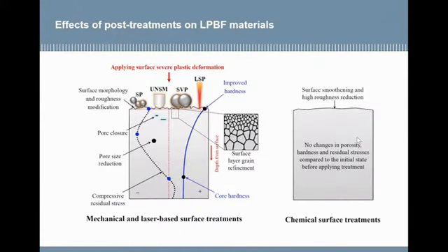The mechanical surface treatments, including also the laser shock peening, are supposed to not remove any material, but they are just regulating the surface roughness due to the severe plastic deformation. They are also inducing compressive residual stresses. They can cause surface grain refinement and gradual change of the hardness of the material towards the core. In some cases, as I'm showing you in the next slides, we have been able also to close the pores that are very close to the surface with these severe plastic deformations.